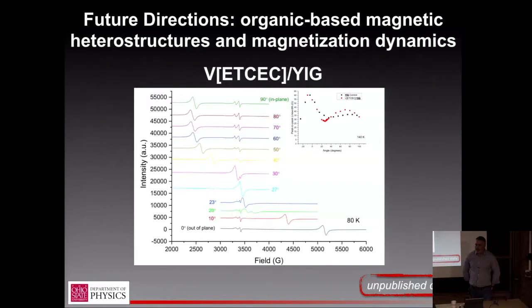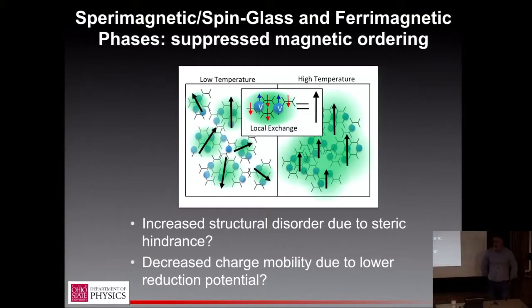What's special about vanadium? It's not clear. There's been a lot of prior work in this area with replacing the vanadium with other transition metal atoms, and almost all are magnetic with lower Curie temperature. My guess, and this could be my own prejudice showing, because I did a lot of work with gallium manganese arsenide as a PhD student, is that it's this high temperature stabilization of the magnetization, and you want exactly 5d electrons to make that go. I can't prove that, but that's my best guess about what's special about vanadium for this system.